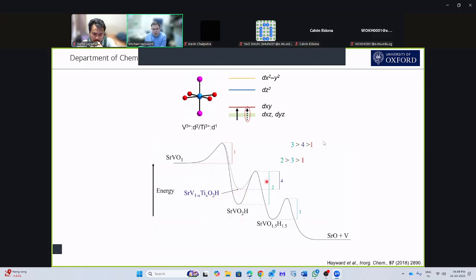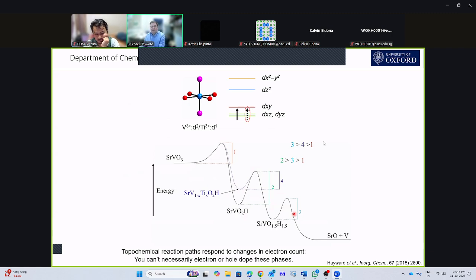And now barrier 2 changes to the size of barrier 4, which is now smaller than barrier 3. So I can get over this barrier and not that one. And so now I can make this intermediate phase. And you can see what that shows you is the electron count is changing the activation energy, and so it's